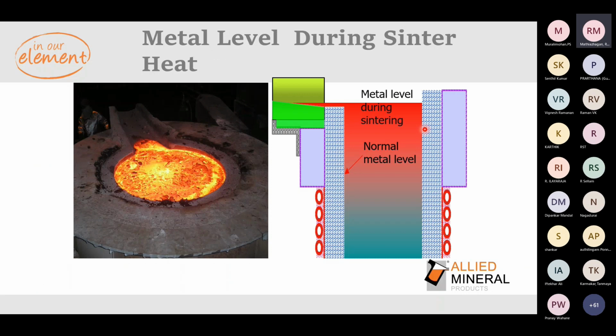So normally during the sintering, we ask to bring the liquid metal as far as the top. You can see this is the normal metal level, and during the metal sintering, bring it till the top. You can do this for at least 3 to 5 linings, and then you can go down to the normal metal level, so that the lining is sintered properly throughout.